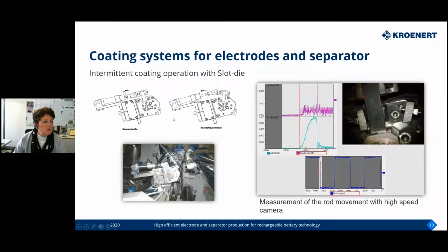The situation is, as soon as you have a valve technology where you do the start and stop operation, the valve is always in front of the die, which means the way from the valve through the die up to the area where you transfer the material to the substrate is very long. And we learned already that battery slurries are thixotropic, so they act very sensitive to shear force, and due to that long way, it can happen that the accuracy of the intermittent process is not good enough.